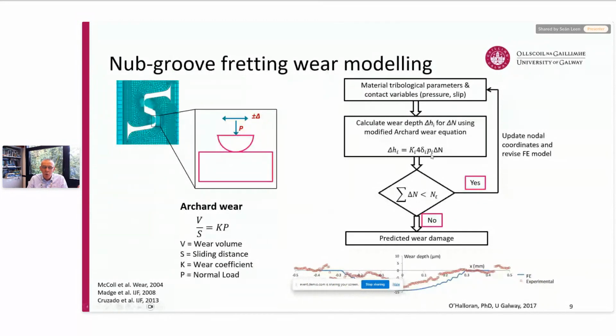And ultimately, what we're looking at is a cycle counting or a cycle stepping type approach, where we accumulate various numbers of delta n cycles, and we calculate the wear during those cycles, and we also calculate the fatigue damage during those cycles. But in this case, I think this slide here is just showing the updating of the wear of the contact geometry associated with the wear. And at the bottom, you can see a sample comparison from Sinead's work. Sinead O'Halloran is the PhD student who did this work, between her finite element model and the measured profile of the wear scar, giving reasonable comparison, I would say.